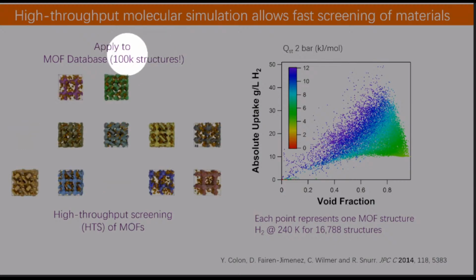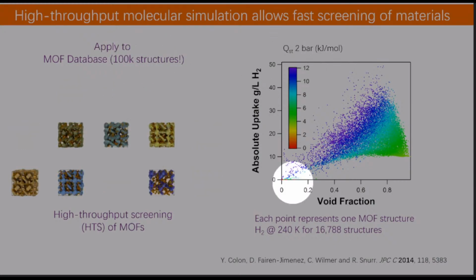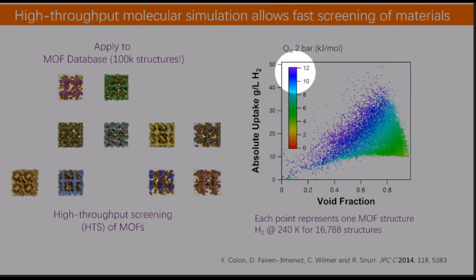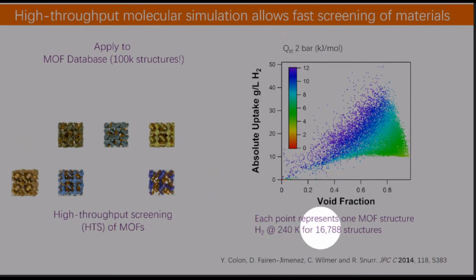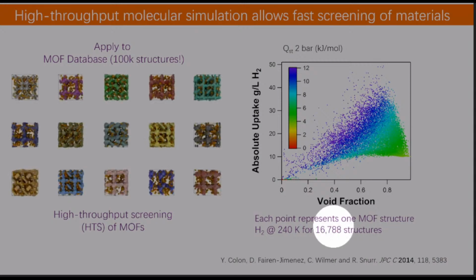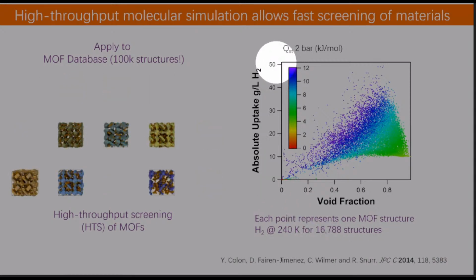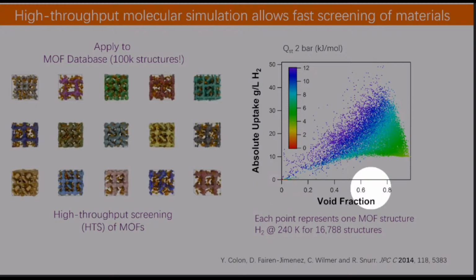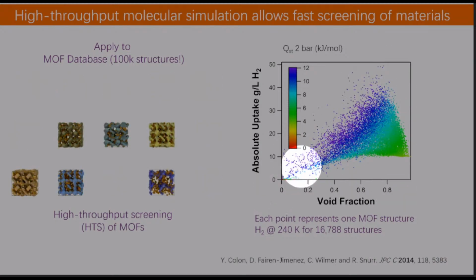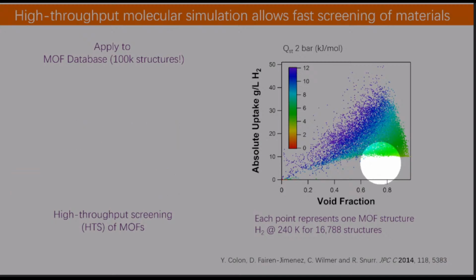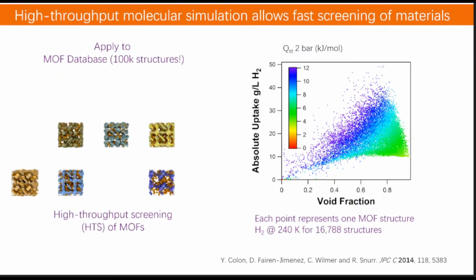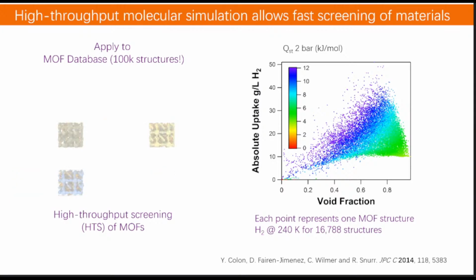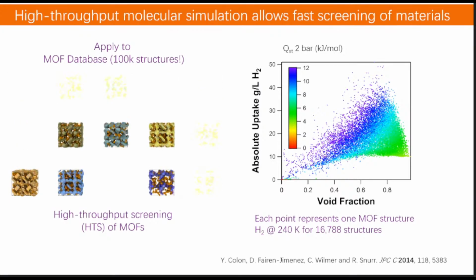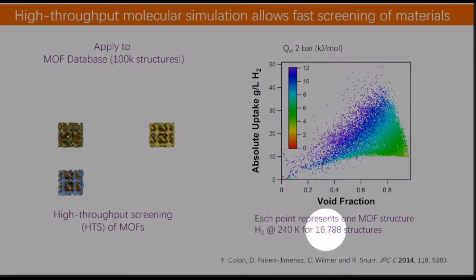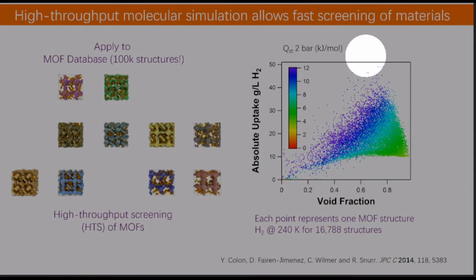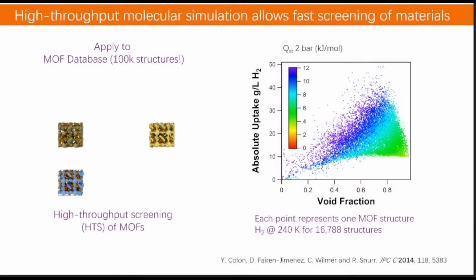We can really work with 100,000 different structures, and we can get these kinds of maps that you can see here. This is basically for hydrogen adsorption on 16,000 different metal organic frameworks. And what you can see is grams of hydrogen per liter of material as a function of the porosity. And every single point you see here is the result of one single Monte Carlo simulation. This is something that we can run in about one month's time. But if you try to do this experimentally, obviously that's going to be impossible. This is synthesizing 16,000 different materials and running 16,000 different adsorption isotherms for hydrogen.